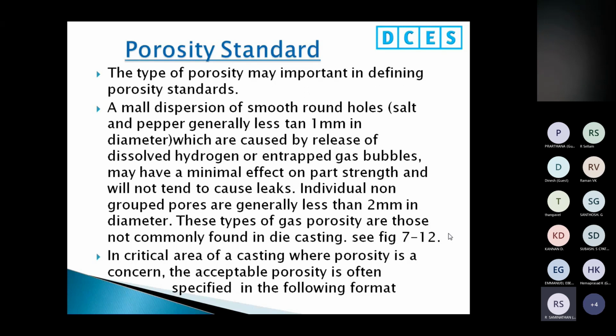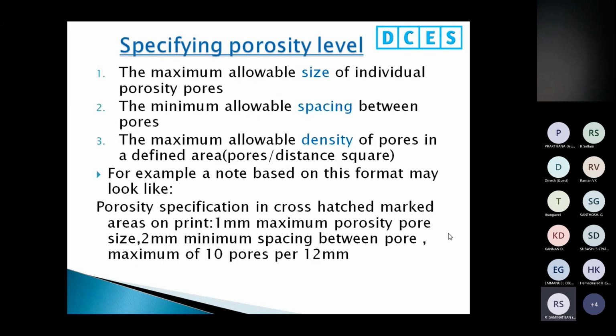Individual non-grouped pores are generally less than 2 mm in diameter. These types of gas porosity are not commonly found in die casting. In critical areas of the casting where porosity is a concern, the acceptable porosity is often specified in the following format. This is one type of methodology to define the porosity, specifying the porosity level: the maximum allowable size of the individual porosity, the minimum allowable spacing between two pores, and the maximum allowable density of the pores in a defined area. That means pores per distance squared. For example, in 1 square centimeter, how much porosity is acceptable, with the density, spacing, and size.